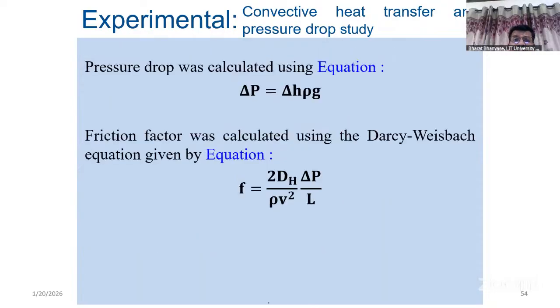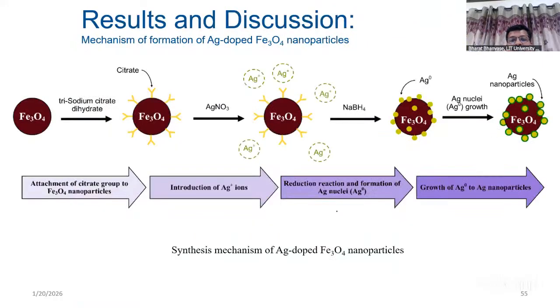Then pressure drop calculation was done by delta H rho G, which was done by Darcy-Weisbach equation also. Friction factor was calculated from this, from delta P. That delta P you can substitute here, length of pipe, velocity, density, and diameter. So from that you can calculate the pressure drop.